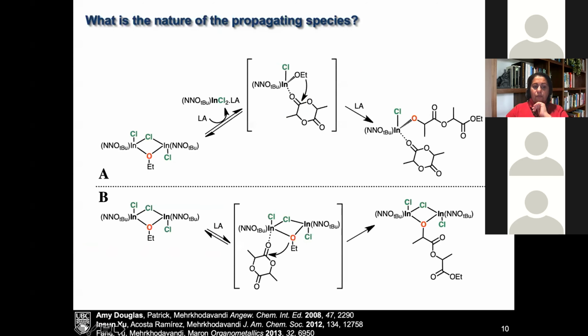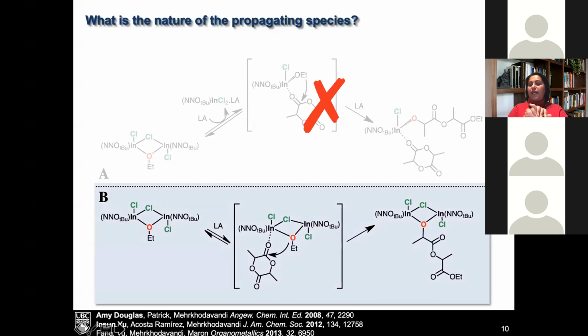And this is really a feature of indium because of the larger ionic radius. The stability of this dinuclear center allows for the two metals to basically protect that chain end, and that protection of the chain end prevents it from going back and carrying out any other side reaction that would prevent chain propagation and lead to chain termination.